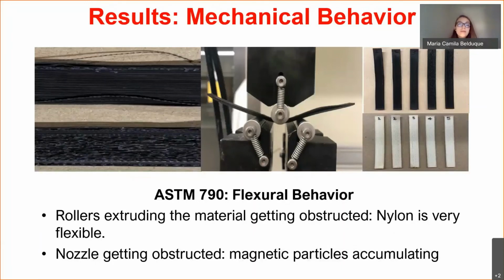To determine the mechanical properties, we did flexural tests on the neat nylon 12 and the composites following the ASTM 790. So 5 samples of each material were 3D printed. This process was constantly monitored due to the rollers that pushed down the material getting obstructed. But the temperature was increased to 225 degrees for neat nylon 12 and to 235 for the composites. However, the same problem occurred for the latter at random stages of the printing process.